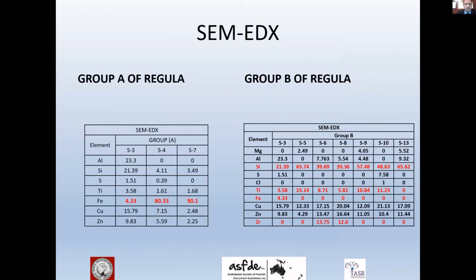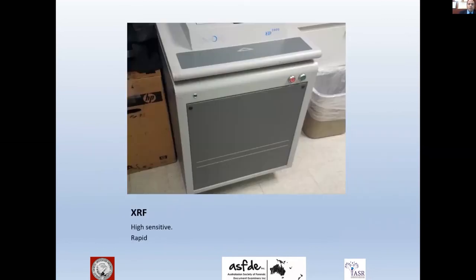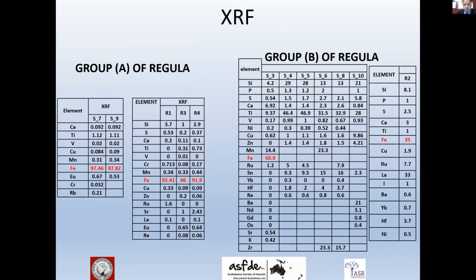To further examine these two groups, we used quantitative analysis by SEM-EDX and XRF to give a complete elemental picture for the production of 15 digital laser printing machines. According to the results, one group showed a high percentage of iron, and the other showed high percentages of silicon and titanium. XRF gave a full picture of the elemental composition used in the production of all 15 laser printing samples. Every laser printer machine has an elemental fingerprint with characteristic percentages.